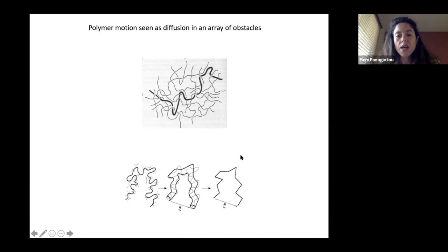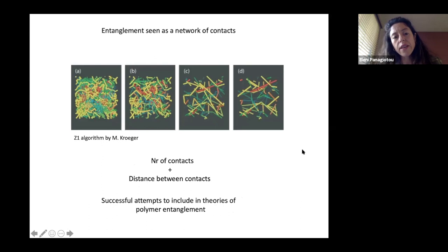So these time scales and length scales correlate relatively well with experiments. And so the way that in polymer physics entanglement is often studied is by trying to derive these characteristic length scales. And how to do this? We do molecular dynamics simulations to get a polymer melt, let's say this one. And this looks like a mess. So we want to study entanglement in that, or we want to find out things about that tube I was describing earlier, which is a simplification of how to look at entanglement. To do that, let's suppose everything is fixed for a moment, the ends or some points on the curves of these macromolecules are fixed.